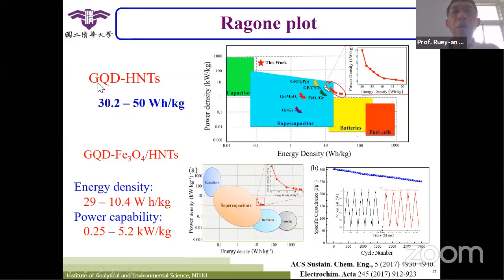Here you will see that when you only have the GQD and HNT, their power density actually will be high, but the energy density is only around 30 to 50 watt-hours per kilogram. When we add the iron oxide, their energy density decreased a little bit, from 29 to 10.4. The reason is that we count the energy density and power density by weight. And HNT and GQD are actually quite light, so for every kilogram they can have more GQD on the surface, so their power density is high. Since iron oxide is much heavier than GQD, even though their capacitance is high, their energy density decreased a little bit. But you will see that for the nanomaterials, with the iron oxide inside or not, their values are good.